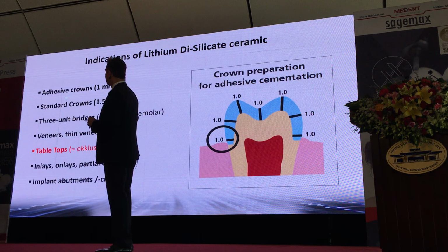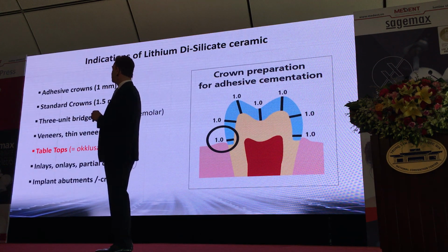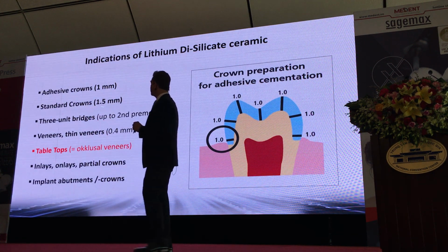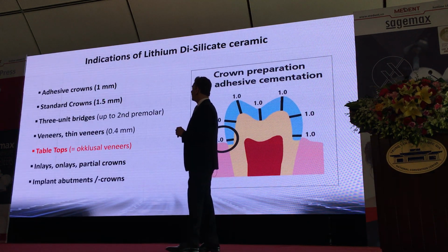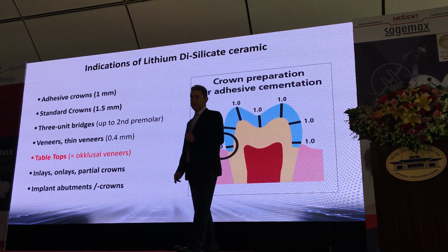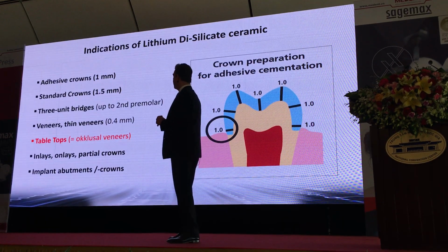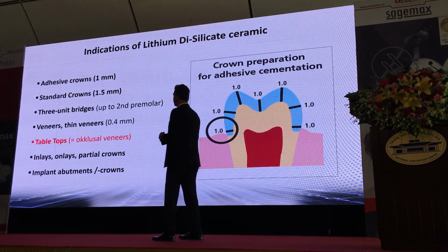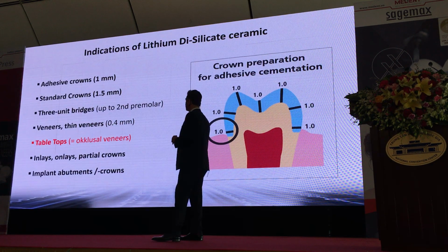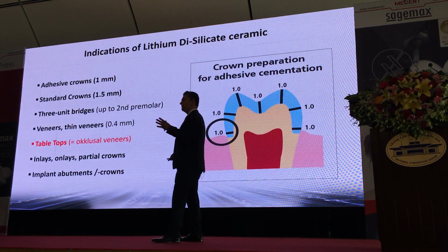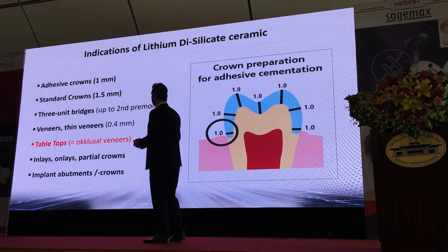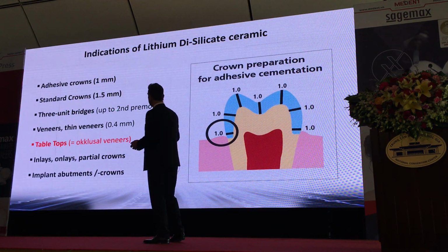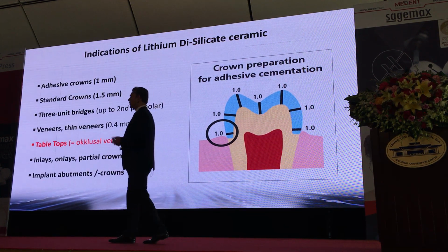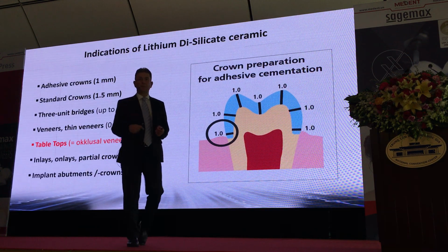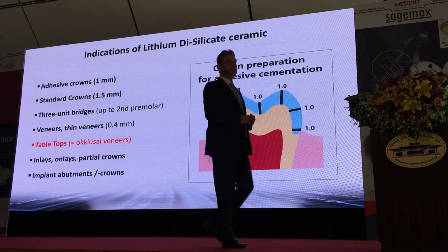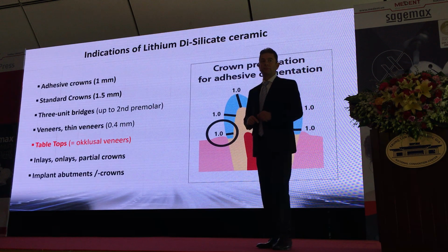But if you are bonding the crown, let's say an adhesive cementation, you can decrease the minimum thickness from 1.5 to 1 millimeter only. Okay? And then, of course, we can do veneers, and also thin veneers, so 0.4, 0.3 millimeters. Three-unit bridges, but you cannot replace molars. So the terminal abutment for the bridge would be the second premolar, right?